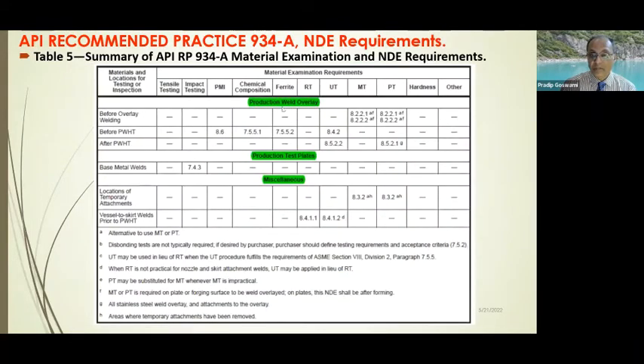And this is a requirement for the production weld overlay. Before weld overlay, you have to do MT or PT. Generally, PT is preferred; that's from my experience I have seen. Before post-weld heat treatment, you have another set of requirements, that is, you need to do PMI, chemical, ferrite test, and UT. And after post-weld heat treatment, you have to do ultrasonic. You note here the production weld, the ferrite test is to be done before post-weld heat treatment. Generally, after post-weld heat treatment, there is a tendency for some increase in the ferrite due to certain specific reasons. But that is why the recommended practice is to check the ferrite before post-weld heat treatment.